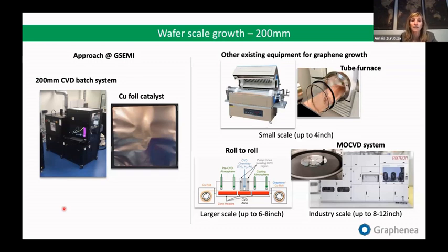So only with thermal, only with heating, you can get quite good quality graphene. We need a catalyst, so we use copper foil as the catalyst. This is an actual image of the holder that we have in the reactor. This is the system that we have in our clean room, and we can grow 200 by 200 millimeter copper. Well, graphene on copper, sorry.